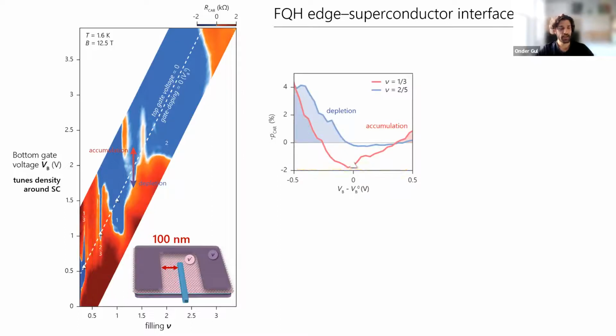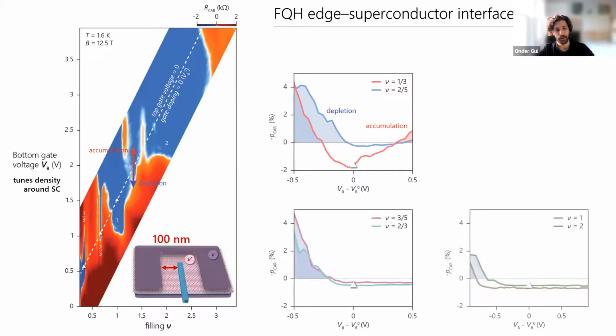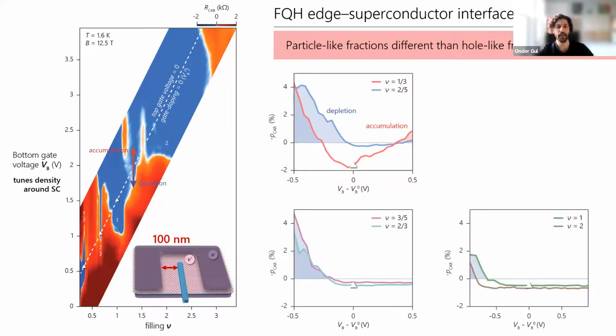So in particle-like fractions, for example, 1/3 and 2/5, we find that the negative signal disappears when the density around the superconductor deviates from the electrostatically neutral condition. Here it's seen as the 0. When one increases or decreases the density, the negative signal disappears. This is shown as the depletion case for decreasing density and the accumulation case for increasing density. The negative signal is present only in the neutral condition. In hole-like fractional states and integer states, the negative signal disappears only for decreasing density, for the depletion case. Increasing the density away from the neutral condition has virtually no effect in the measurement range.